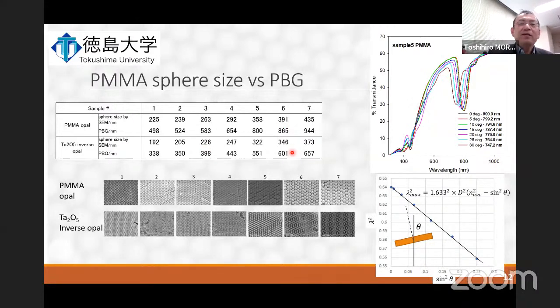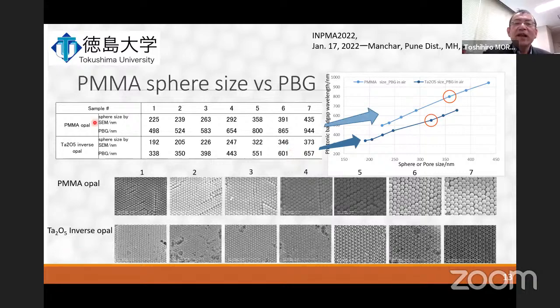So we plot these data. This is the sphere or pore size dependence of the photonic band gap. This is for the PMMA opals, and this is the tantalum oxide inverse opal. You can see the almost linear relations between these.